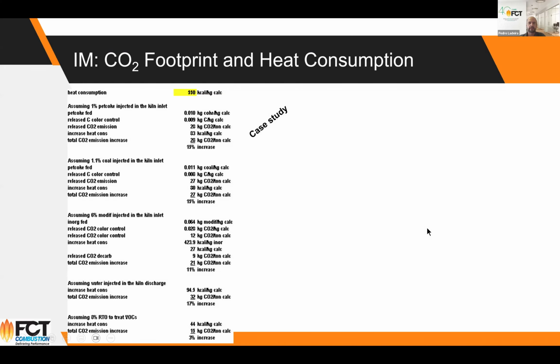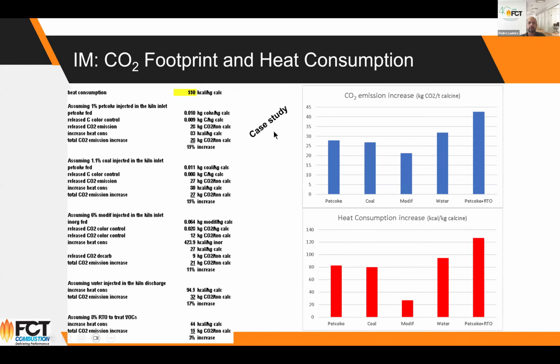And the calculation that we've done for a case study is that if you consider that you are using pet coke in the feed of a kiln to control color, or coal, or if you're using modifiers, which is our proposition here, or if you use water, or if you use pet coke but you still have to get rid of the VOC, these are the figures. You're going to have an increase of CO2 by controlling color with pet coke or coal, but a slightly better or less increase in the heat consumption or the emission increase, and water will be a lot, and then you have RTO as the one that takes a lot of energy to get rid of the VOC.